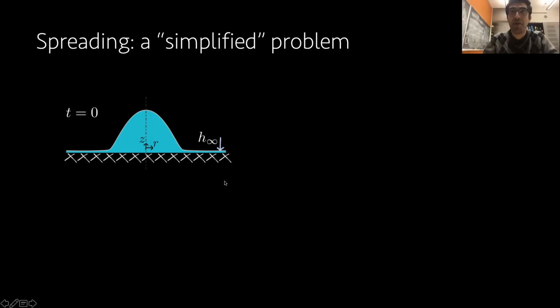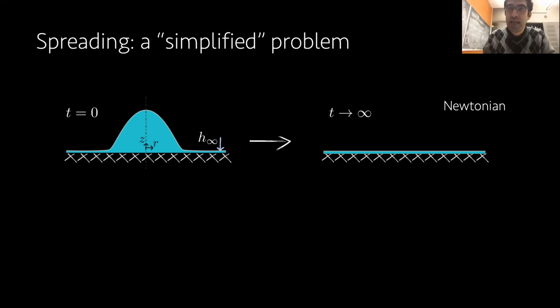Okay, so here is what I call the simplified spreading problem. I have a solid surface that is pre-coated with a thin film of thickness h infinity, and I put a droplet that is much larger than that on top of the surface, and I let it spread. If the droplet is Newtonian, you can easily guess that as time goes to infinity, this droplet spreads until it becomes fully flat. Nothing stops the droplet from spreading on the surface, right?